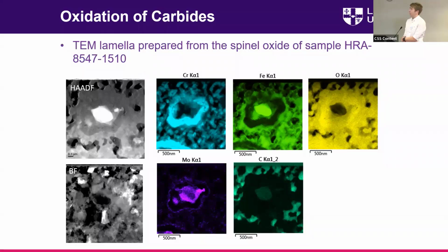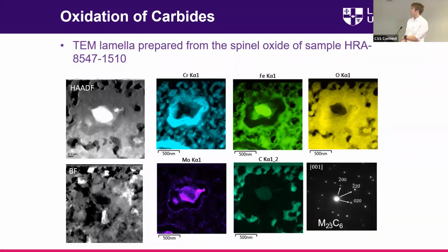So I performed selected area diffraction to index this, and it was M23C6, so it's showing that the carbides are able to potentially resist oxidation as the oxide front is moving through the material, and remain within the oxide for potentially thousands of hours. Well, we think it's because of the chromium-rich oxide, which has preferentially formed at the oxidation front, and that protects the inner iron-rich carbide region from further oxidation.